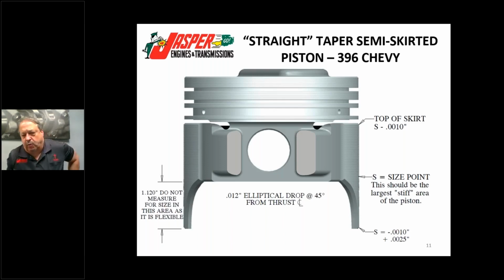Skirt coating, for the way that we use it, and we use several different, but basically a D10 or an abradable type. That's why we'll run 1,000th minimum clearance on our forgings or castings in a gas engine, and depending on what we allow it up to and what our tolerances, we may get up to 2.2 or 2.5 thousandths clearance at the max. But that's the true size to the aluminum. The skirt coating we don't count.